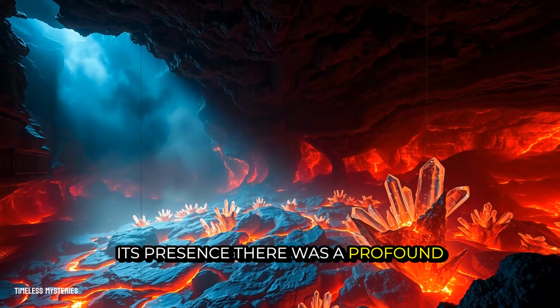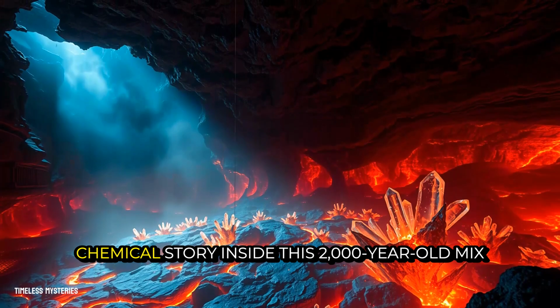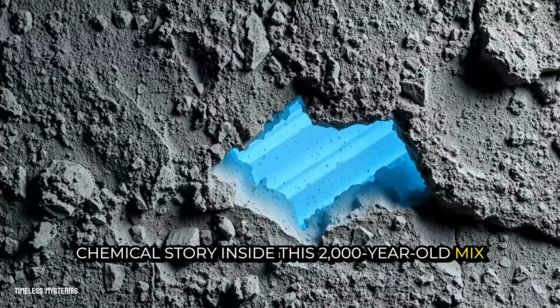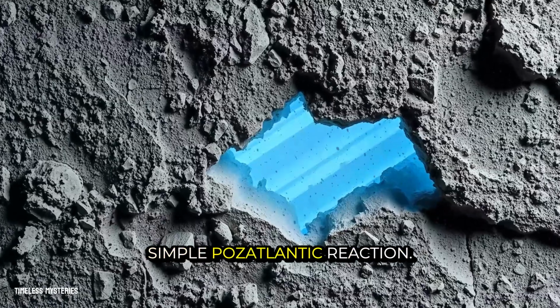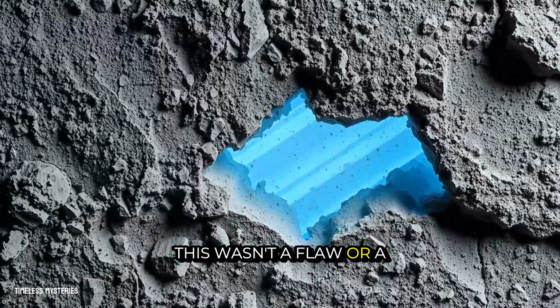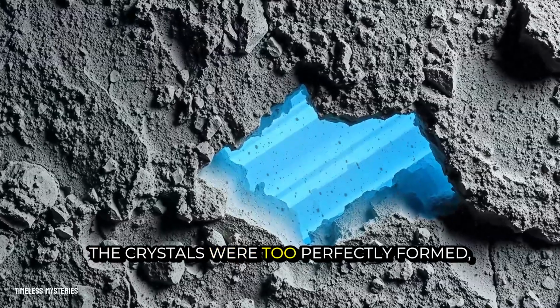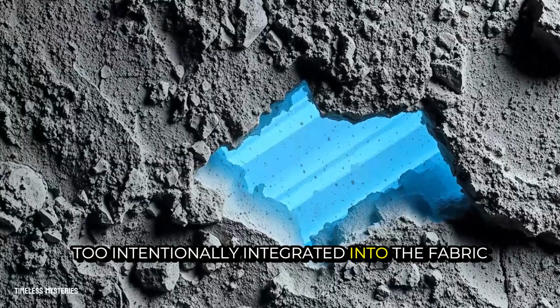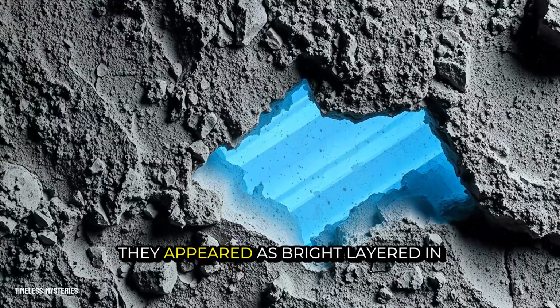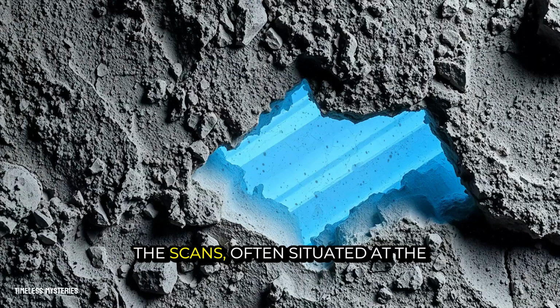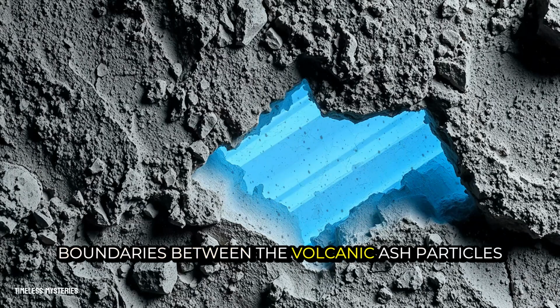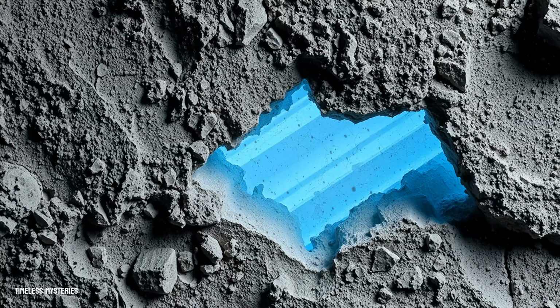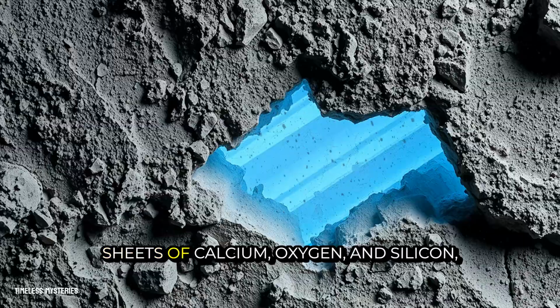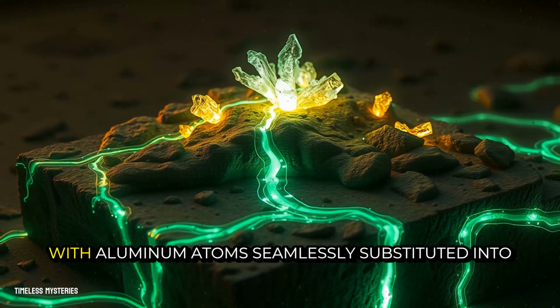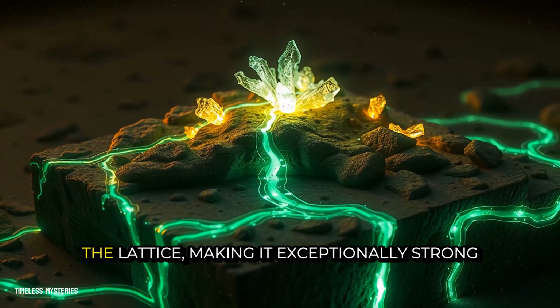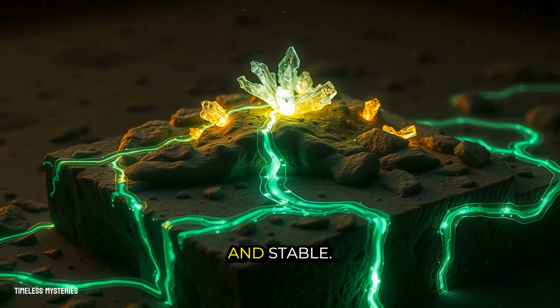Its presence there was a profound anomaly, a clear signal that the chemical story inside this 2,000-year-old mix was far more complex than a simple pozzolanic reaction. This wasn't a flaw or a contaminant. The crystals were too perfectly formed, too intentionally integrated into the fabric of the material. They appeared as bright, layered inclusions in the scans, often situated at the boundaries between the volcanic ash particles and the binding matrix. Their structure is unique, composed of sheets of calcium, oxygen, and silicon, with aluminum atoms seamlessly substituted into the lattice, making it exceptionally strong and stable.